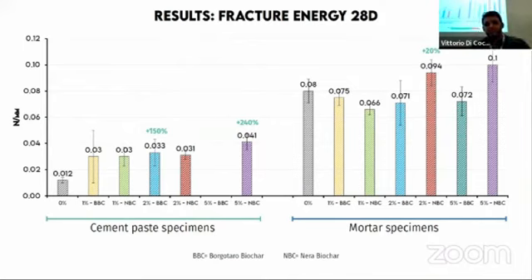This could be the most promising result, because in the case of cement paste specimens, we reach more than double the capacity of the reference one, reaching more than 150% in the first stages, which means 1% and 2%, and more than 240% when 5% of Nera biochar was used. In the case of mortars, we improved by 20 and 25% when 2% and 5% of Nera biochar was used. It could also be seen that overall, Borgotaro biochar does not have the same capacity to improve the mechanical properties as Nera biochar.